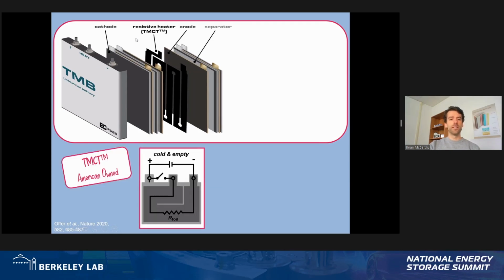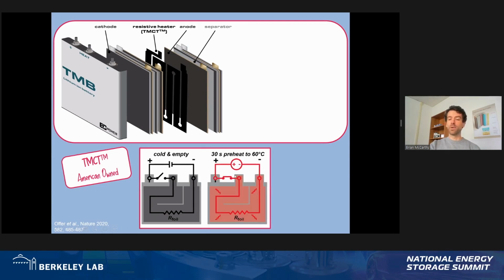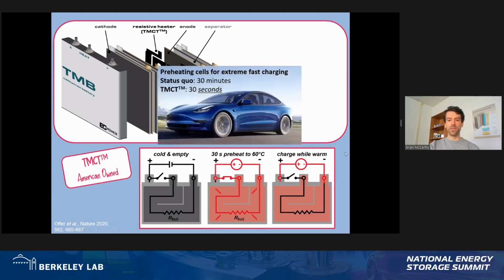And we think about a simple circuit diagram here. When this switch is open, nothing is happening. But if you close that switch and connect your cells to an external charger, you run current through the circuit and generate heat very quickly, uniformly from the inside out. And then you can safely fast charge. Now, the major advantage here is that you take the status quo liquid cooling time from 30 minutes and you drop it to 30 seconds.